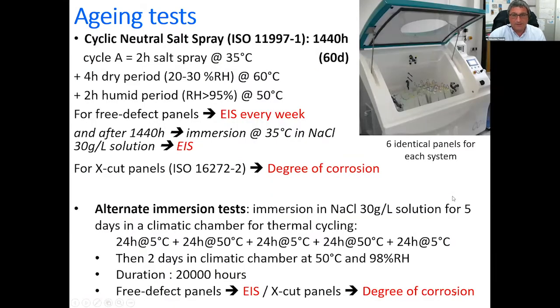And now these are the cyclic tests, the cyclic aging tests. We've got the cyclic neutral salt spray, which is cycle A. It means 2 hours of salt spray at 35 degrees C, then 4 hours of a dry period with a relative humidity between 20 and 30% at 60 degrees C, and then followed by a 2-hour humid period with a relative humidity higher than 95% and a temperature of 50 degrees C.